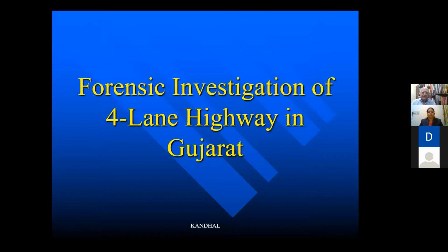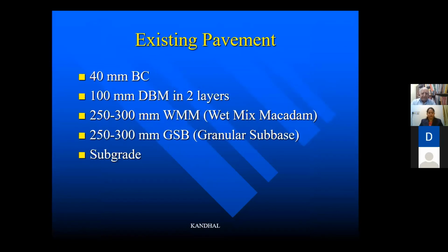Now I'm just showing you 2 forensic studies I did. One was a 4-lane highway in Gujarat. The existing pavement on that 4-lane had 40 millimeter bituminous concrete as the surface on the top. Below that, they had 100 millimeter dense bituminous macadam in 2 layers. So these are 140 millimeter of bituminous surface. Then 250 to 300 millimeter WMM, wet mixed macadam, and here the GSB, and there is a subgrade.